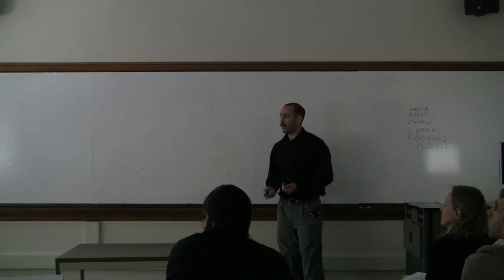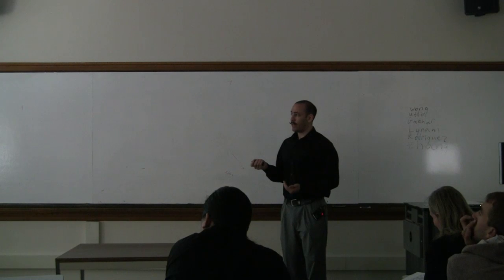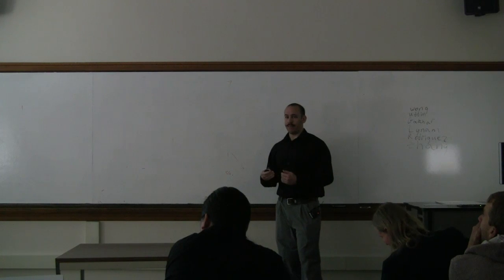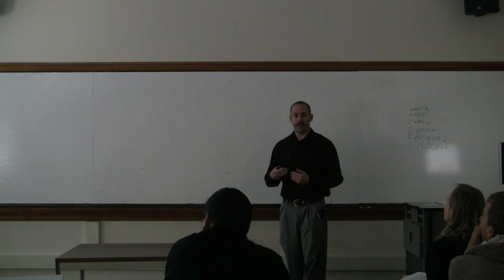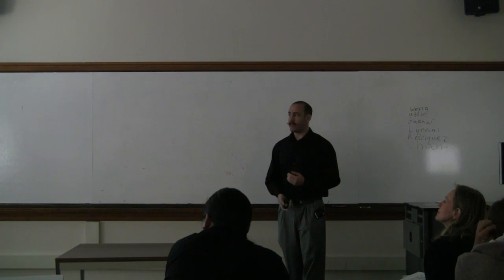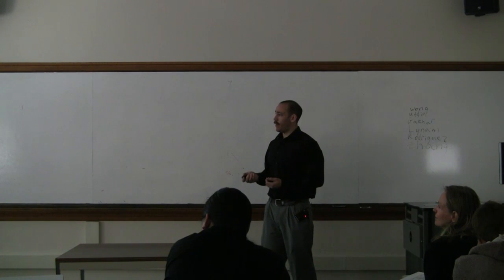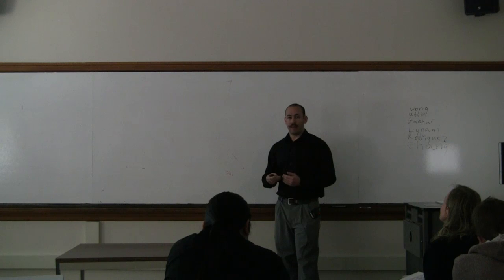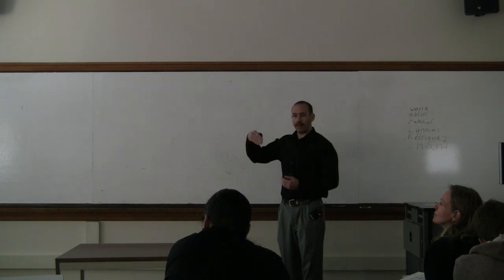Now, why is chromate conversion coating so important to the industry? Well, here's a model of how they form chemically. So on the base layer of the aluminum alloy, you have chromium-3, which provides a barrier layer. And then on top of that, you have the majority of the ions forming at chromium-6, which has very unique properties. So we have the barrier layer to start off with. Then we have a bipolar layer. So since we have the two valencies, we have a layer that is formed that will prevent cations from migrating off the surface of the metal and prevent anions from leaching into the surface and corroding the alloy.